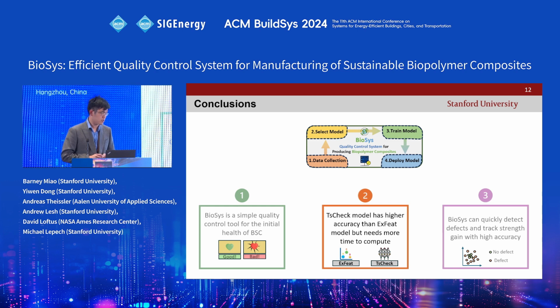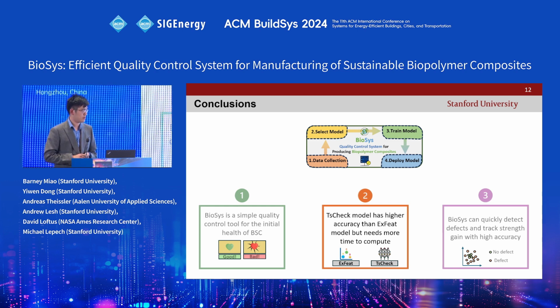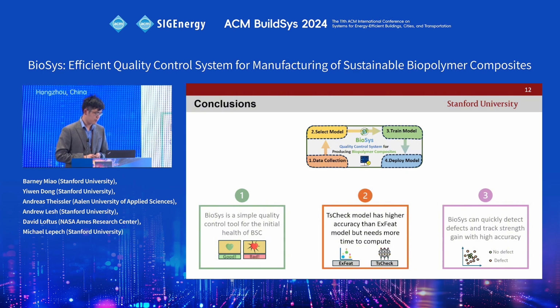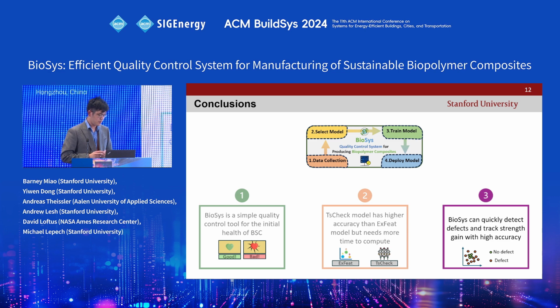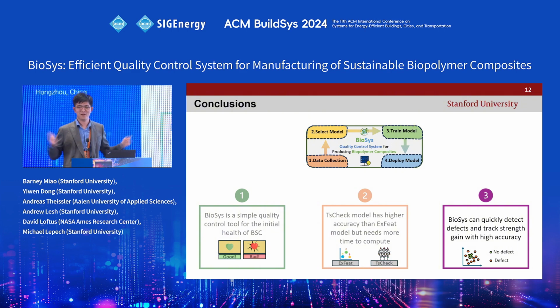But it needs a little more time to compute, probably a few minutes instead of a few seconds, depending on how fast you want your results. And if you just want a rough guess, there are multiple methods you can use. And also, BioSys can relatively quickly detect and track the strength gain and defects with relatively high accuracy. So if you're sleep deprived or anything like that, these are three points to take from the presentation.